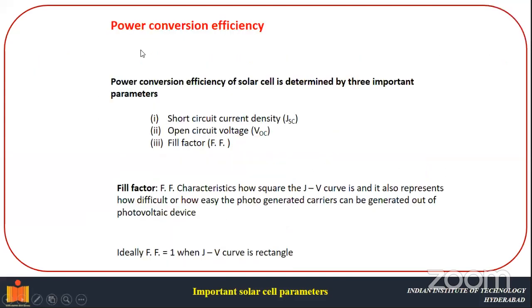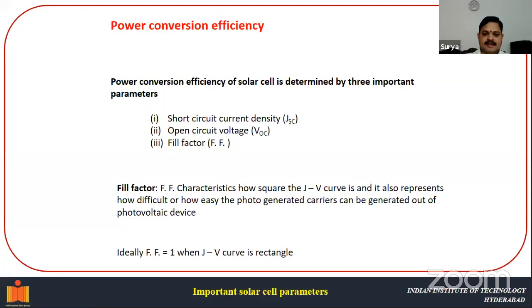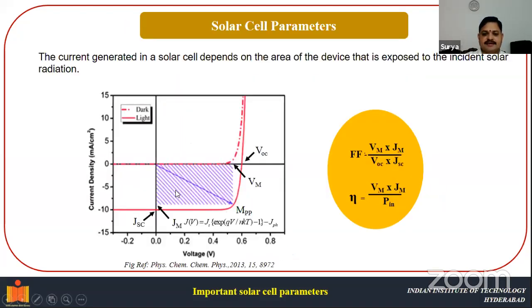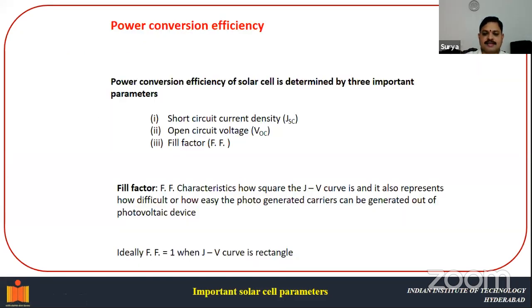So the power conversion efficiency of a solar cell is determined by three important parameters: short circuit current density, open circuit voltage, and the fill factor. The fill factor characterizes how square the JV curve is, as I just mentioned, and it also represents how easily the photo generated carriers can be extracted out of the photovoltaic device. So this fill factor is a very important parameter to characterize any solar cell device. Ideally the fill factor must be 1 when the JV curve is a rectangle. Like for instance, if you have a rectangular JV curve, you can actually get the fill factor 1. That means the maximum amount of sunlight you can convert as current.